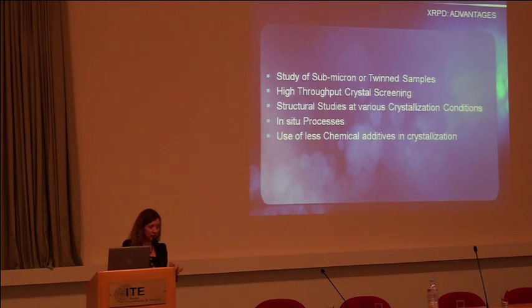We usually solve protein structures at various crystallization conditions, and this is a way to create a phase diagram. In material science, this is very common. In protein crystallography, this was not a common approach, maybe because it was not possible to create a nice single crystal at various conditions. But with our methods, we can, at least up to a certain point, relax this limitation. And as I'm going to show in the following slides, we tend to create phase diagrams for each protein in order to create a more complete structural picture at various crystallization conditions.